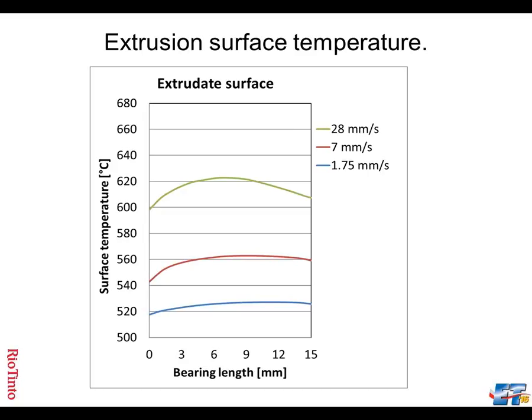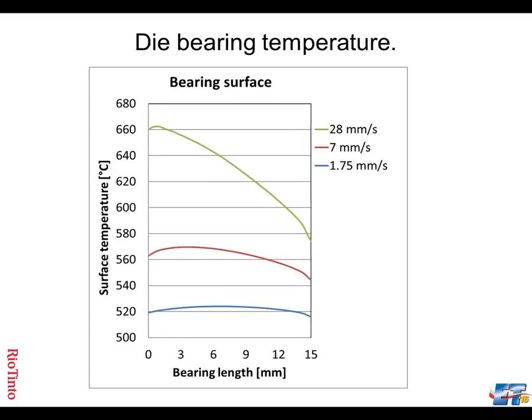This is the profile. If we look at the other data, which was the temperature of the die, it gives a very different picture. It tells us that the temperature of the die, again, is a lot hotter at high speed, but the temperature is highest at the entrance of the bearing, and it drops throughout the length. This maybe is not expected, but it certainly does tell us why dies wear at the entrance part. They tend to start washing out near the front of the bearing, not at the very entrance. And it tells us there is a difference between die temperature and extrusion temperature.